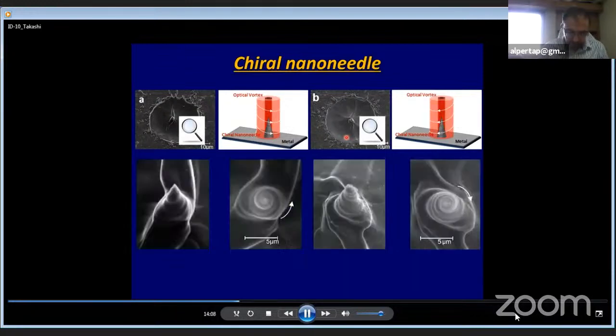At that moment we can see how this needle is twisted. A right-handed optical vortex can create a right-handed twisted needle. A left-handed optical vortex can create a left-handed twisted needle. That's quite interesting. Orbital angular momentum can directly twist the melted tantalum. This is good evidence.